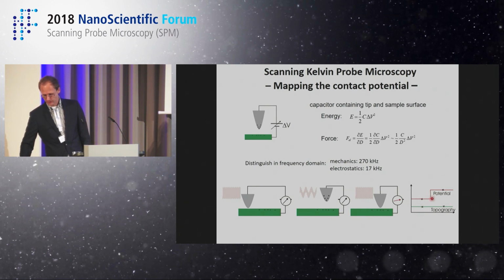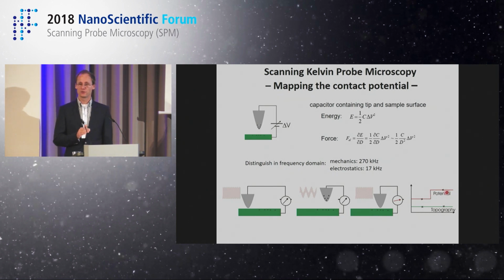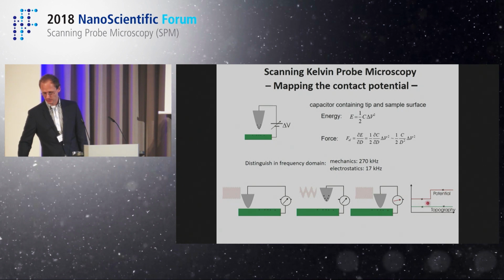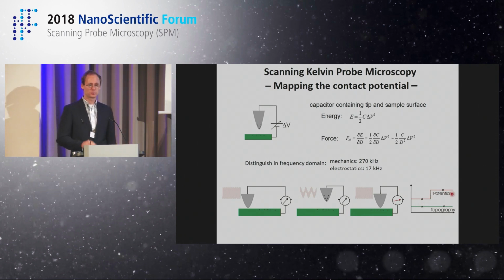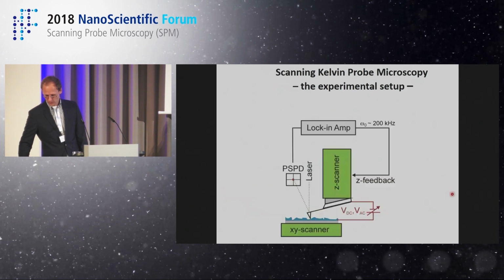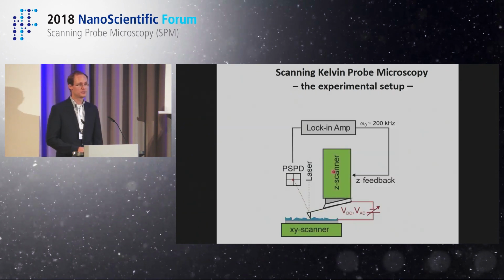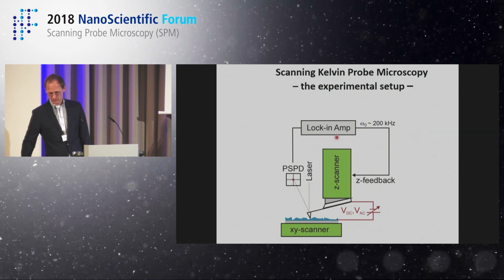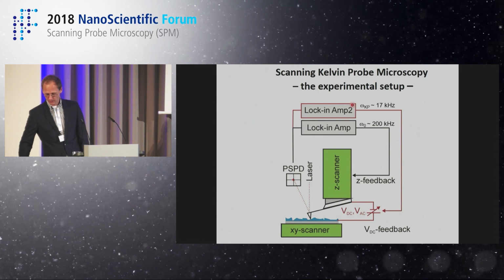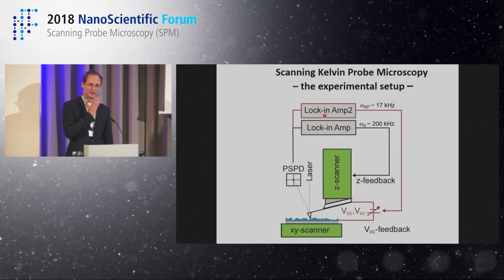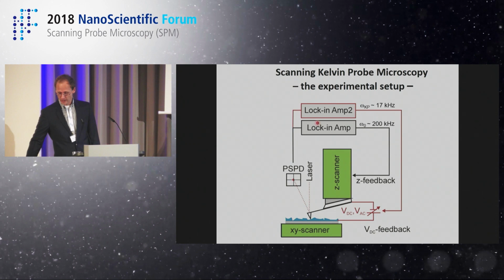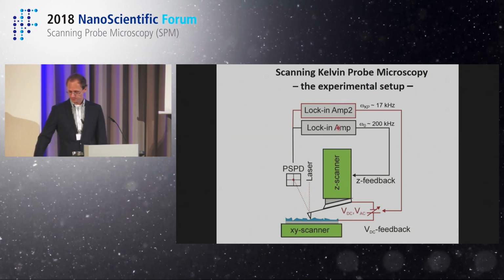In addition, we can map the DC potential that we apply to our tip in order to nullify these forces, and we would get an additional channel of data acquisition, which is just called surface potential, which would contain information about the electrostatics. Okay? And that's how scanning Kelvin-probe microscopy works. Of course, the technical implementation needs, in addition to the usual non-contact with a single lock-in amplifier, as in the NX10, a second lock-in amplifier in order to precisely separate the frequency at which your electrostatic oscillations occur. If you have these two lock-in amplifiers in your instrument, which is the default for the NX10, the nice thing is you can do just one scan and immediately acquire both data channels without artifacts.